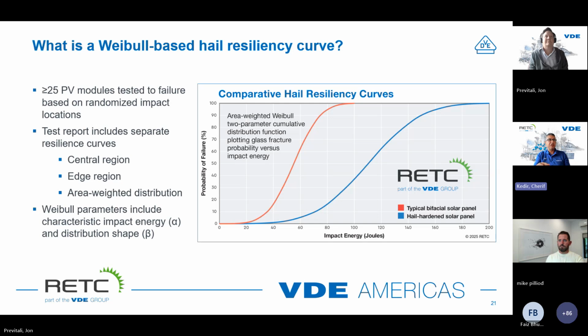Some are going to fall in the corner and the edges, and a lot of them are going to fall in the center. And the reason why these curves are so tight and so accurate is because we take all of that into consideration. So it goes into the plan. And that's why the key here is we just keep impacting until the module breaks. And we impact certain areas until the module breaks. So we take into account the statistical nature of how a hailstorm could damage a module. And then the next slide is how we do that.